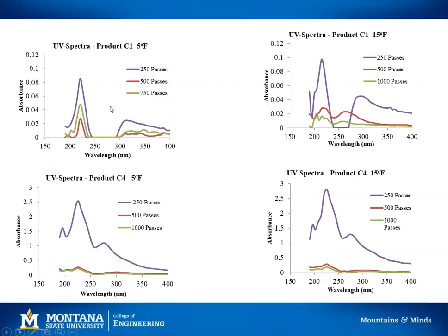Now for the category C products, so C1 and C4, we did the same thing, but the major constituents of these products are not chloride, so we couldn't measure the chloride concentration to determine this. So we used the UV spectra, and we basically identified the characteristic peaks for these different products, and you can see those here. And what you can see is in purple, we have 250 passes, in red 500, and in green we have 750 passes. And again, you can see the same trend that you saw with the chloride-based or ag-based product that was mixed with salt brine. You can see that by 250 passes, the bulk of the product is removed with plowing of the snow, and that only a small fraction remains after 500 and 1,000 passes for these.